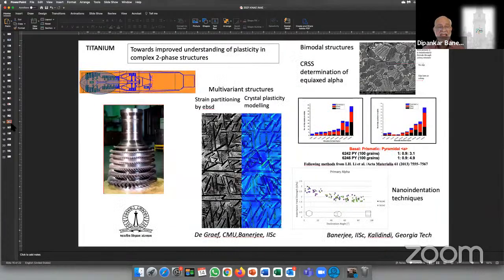The understanding of process capability is supported by the understanding of plasticity in these two-phase structures, microstructures that constitute titanium alloys. So the determination of local properties in such structures, the critical resolved shear stress of various phases through nanoindentation techniques combined with FEM analysis, crystal plasticity modeling to understand the strain development and strain partitioning in such structures, coupled with experimental understanding of strain partitioning. All of these together provide models to understand the mechanical behavior of such structures, for example, under fatigue loading.